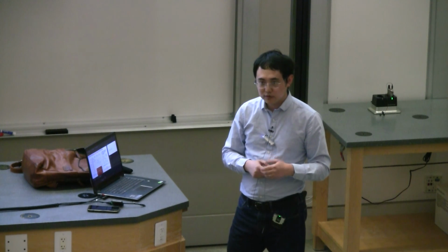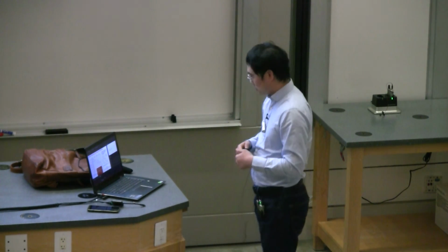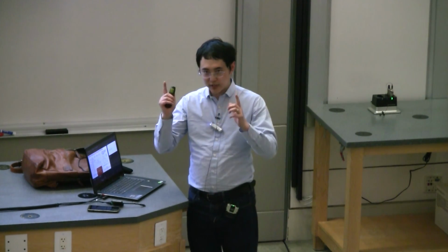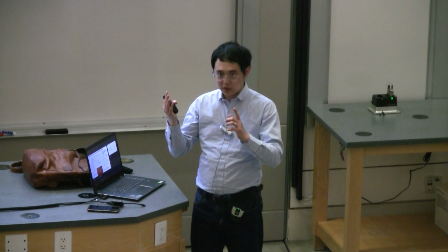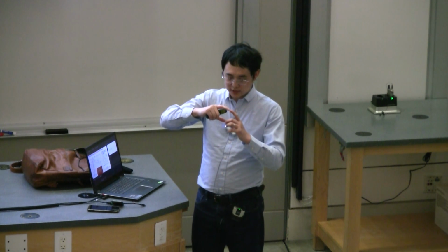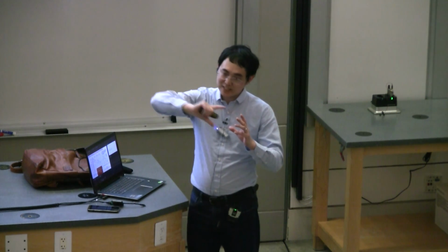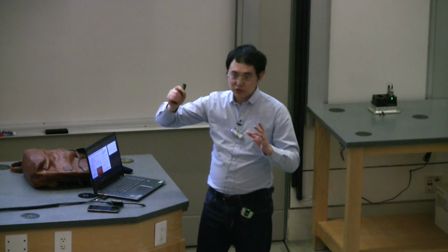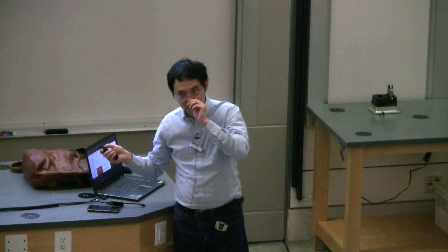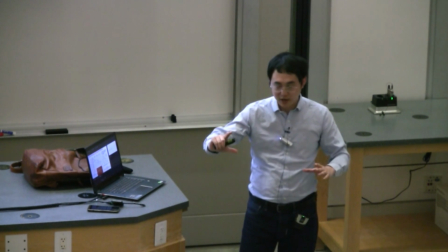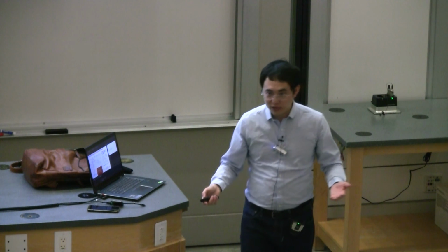And for the other numbers of layers, you haven't definitively seen fractional states yet, but is there still kind of like a diagonal window in ND space? That's right. If you look at the RXX, there's a dip at 2/3 filling in both 4 layer and 6 layers. Phenomenologically, that insulating range is taking a bigger proportion of that stripe, and that eats some of those fractions. I see. So 5 layers somehow is still the best if you want to get the most fractional states out of it. At least the sample we have, there could be variations due to the twist angle difference and things. We haven't got enough devices to map that out.